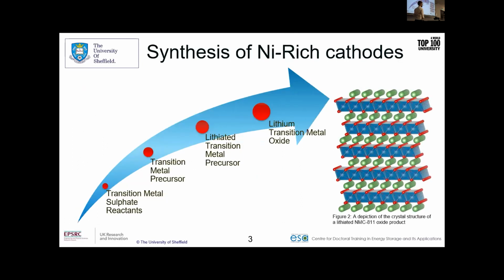So in terms of the synthesis pathway for these materials, we start off with the transition metal sulfates, the nickel, manganese, and cobalt sulfates, and those compounds. That then undergoes a sort of reaction to form a precursor. We then lithiate this and do some solid state grinding in order to mix a lithium source with these transition metal precursors before calcining them. And what we get is this nice layered structure.